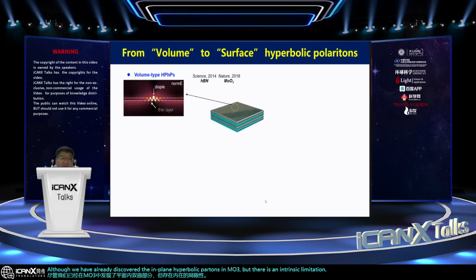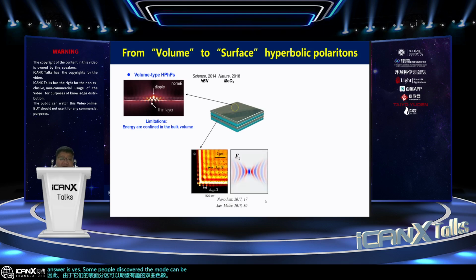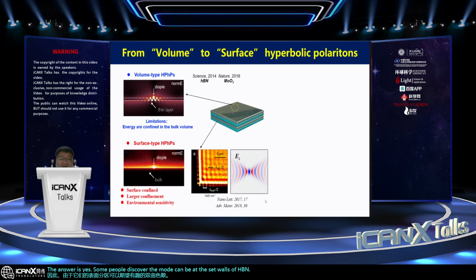Although we have already discovered the in-plane hyperbolic polaritons in MoO3, there's an intrinsic limitation. The most polariton fields are confined inside the bulk volume rather than being surface phonon polaritons, where the fields are mainly confined at the surface, which is more sensitive to the surrounding environment. So can surface polaritons exhibit interesting hyperbolic dispersion? The answer is yes. Some people discovered the mode can be at the sidewalls of hBN. It may have larger confinement and be more sensitive to the surrounding environment.